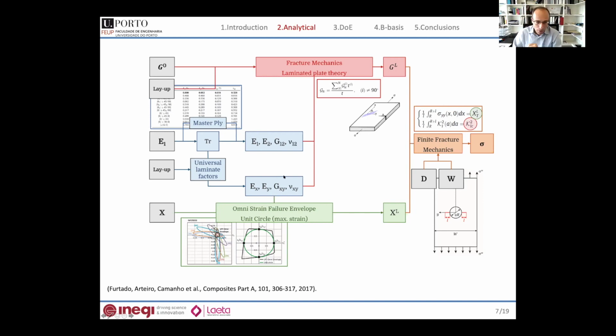that we need again to use in these equations. Also from Steve Tsai's work, we used the concept of omni-strain failure envelope to relate the strength of the 0-degree ply to that of a multidirectional laminate. And in the past, we have also developed some methods that relate the fracture toughness associated with a crack that propagates perpendicularly to the fiber direction to the fracture toughness of a multidirectional laminate. So basically, we just need to know the three material properties: fracture toughness, Young's modulus in the fiber direction, and the strength. Again, longitudinal tensile strength in the fiber direction. We need to know the layup, and we need to know these two geometric parameters to feed our model, okay?